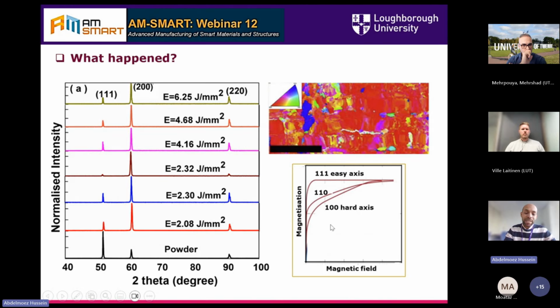So this is a magnetic anisotropy that we have. That's why the material gives us a very high coercivity and poor magnetic properties, because in all our samples the texture has been arranged on, let's say, the bad axis. So that's why it resulted in the poor magnetic properties.